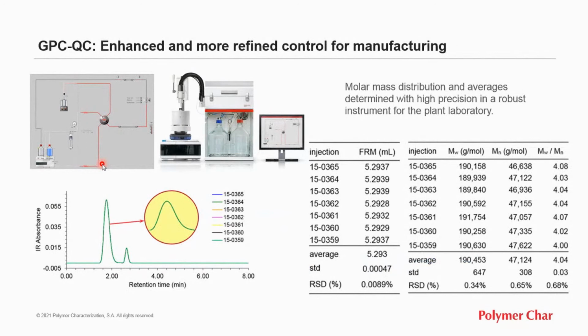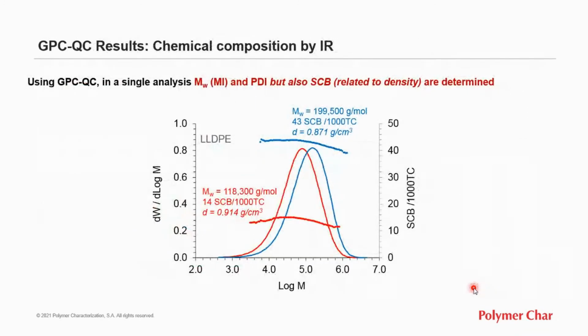It's very precise. We see here in this graph 7 overlaid chromatograms. And in the tables, we see how the precision for MW and MN are really outstanding, and even for polydispersity, all the relative standard deviations are lower than 0.7%. So this tool may complement the existing control based on melt index and density, but with more complex resins, having the full molar mass distribution is actually becoming a need.